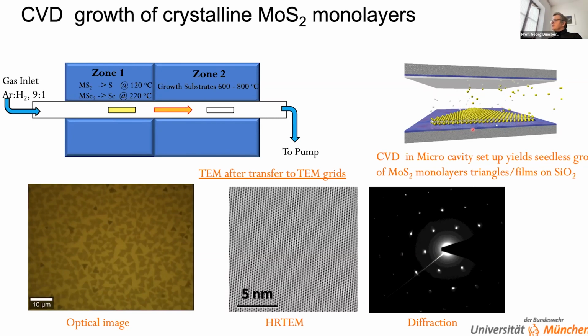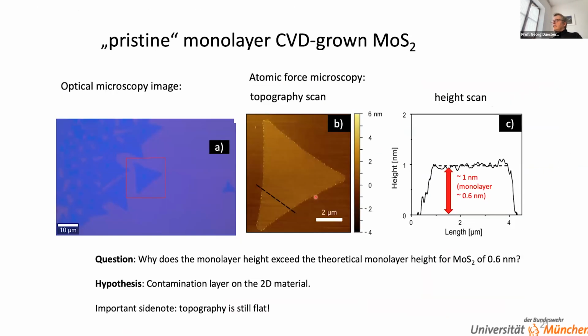So we use a standard process to grow these flakes of CVD MoS2, and again we get these TEM images. We get some nice coverage of this crystalline material. And if we investigate this material when it comes out of the furnace, it looks really, really clean. We can look at the optical microscope as shown here. We can do AFMs, and we can see here in the cross section that we get a material which is about 1 nanometer high, which is a bit puzzling because in theory it should be about 0.6 nanometer. This is often shown for graphene as well, that it appears much thicker in the cross section than it actually should be. Apart from this, it's a very nice, homogeneous and flat surface of the CVD material.